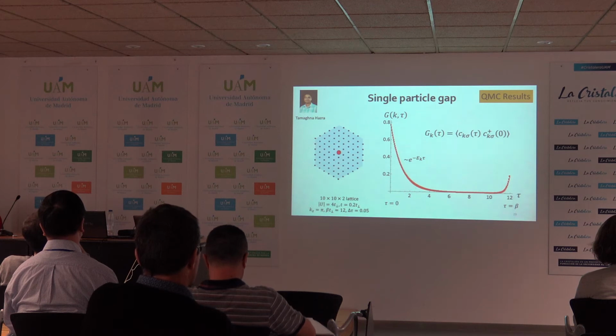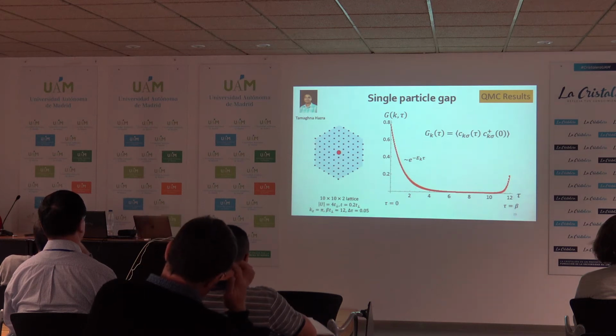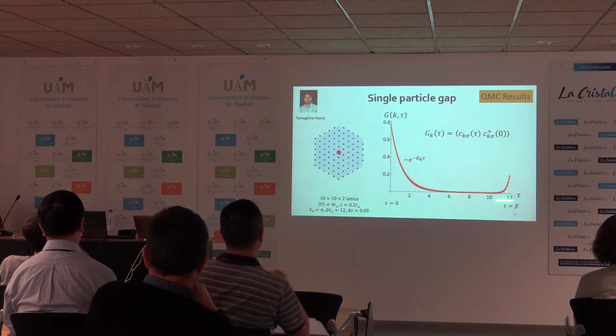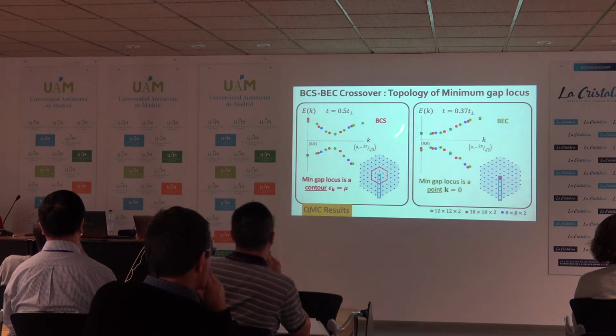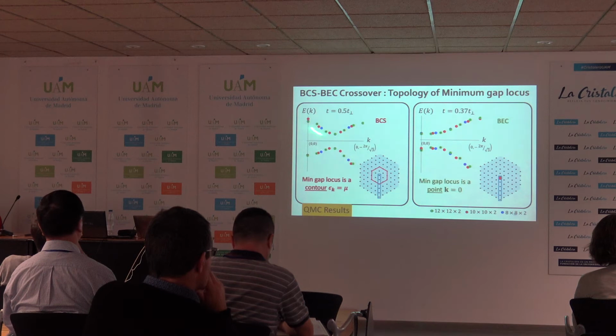I made these sketches just because sometimes these are easy to take in, but here is some quantum Monte Carlo data for the same model that I talked about, where we calculate the Green's function in imaginary time at each point in k space. And from the decay in tau, we can extract the energy as a function of momentum. And you can plot that, E as a function of k. We can do it in both regimes, the BCS and the BEC, and you see this very different dispersion relation.